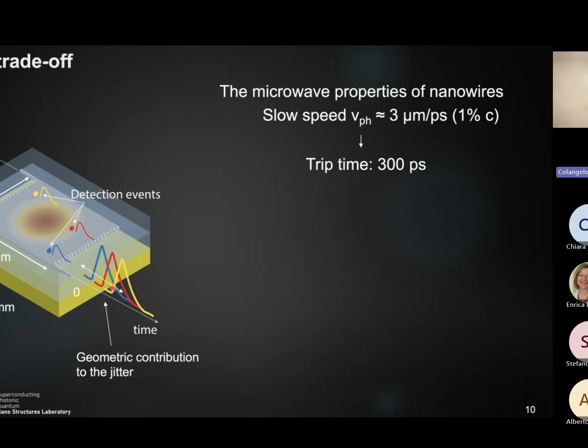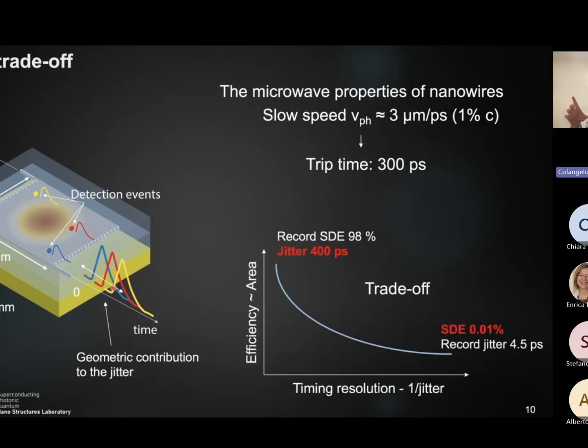And this really creates a problem because we really do want a large detector for active area, but at the same time, a large detector will mean a very high jitter. And so we're actually playing this trade-off game here, where, for example, the record efficiency detector at 98% had a terrible jitter of 400 picoseconds, while the very good detector with jitter at 4.5 picoseconds had a terrible efficiency. So we are playing this game. Now, is there a way to beat the game?